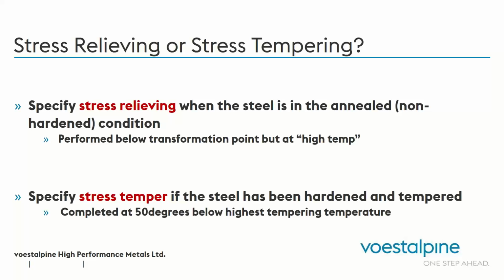So for larger blocks where there's a lot of investment, where there's a lot of size differential within the block, cross-sectional differential, I highly recommend you do a stress relief before hardening. Typically here we do anything over 1,000 pounds. We start to consider stress relief. Stress temper is done at 50 degrees below the highest tempering temperature. Okay, and that is always done on the hardened and tempered material. And it would be considered when, again, you do some welding, some engineering changes, and so forth, and the material does incur stress. So it's really critical. Remove the stresses, and that will reduce cracking in your blocks.